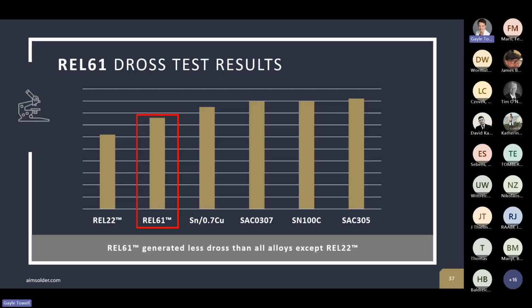Another common question is how it performs with dross. And so dross is something that's highly variable. How much dross forms in a pot doesn't just depend on the alloy, it depends on all of the settings in the production process. So we performed a test under controlled conditions where we melted all of these alloys and subjected them to the exact same conditions and compared how much dross formed. And what we see is REL61 generated the least amount of dross compared to those other alloys. The only alloy that beat it was our high reliability REL22. So if dross formation is concerned, REL61 again naturally drosses less than a lot of those other alloys.